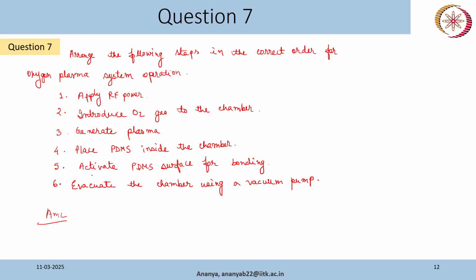So the answer is, first we will place our PDMS inside, PDMS or any other wafer, whatever we are trying to do. Then we will evacuate the chamber using a pump to create a low pressure environment. Then we will introduce oxygen gas and then apply RF power. We will tune the RF power so that we get a very stable plasma. That will create plasma, and after a treatment for a certain amount of time, that will activate the PDMS surface for bonding. We'll stop the process, take the PDMS substrate out, and do the bonding immediately after that.